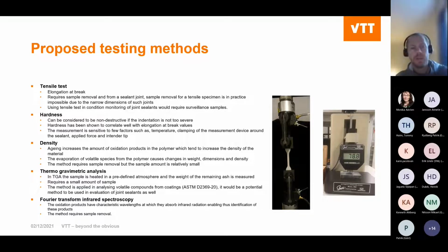Then we have density measurement. Usually aging increases the amount of oxidation products in polymers, and that has an effect on the density of the material. Also, the evaporation of different volatile species from the polymer can cause changes in weight, dimension, and density. Density measurement also requires sample removal, but the sample amount is relatively small, so it might be applicable in this case.